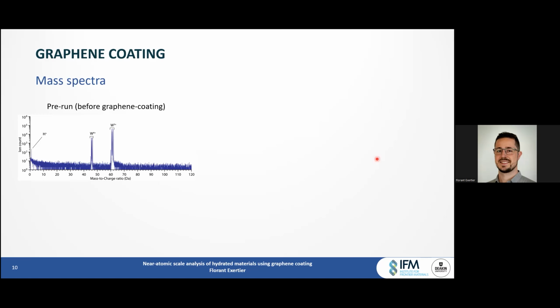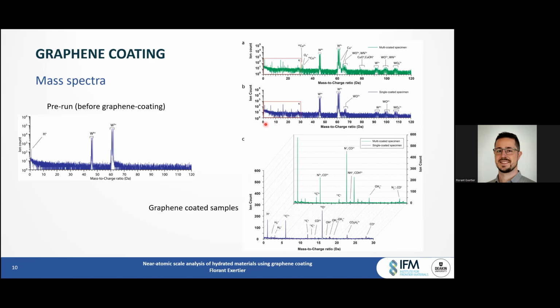So prior to graphene coating, the tips were pre-run in the atom probe up to 5 kV to clean the surface and also to provide shape consistency from one sample to another. So this is the mass spectrum from the pre-runs, which is fairly clean with just a little bit of hydrogen and tungsten 3+ and 4+. And these are mass spectra coming from the multi-coated specimen and a single coated specimen.